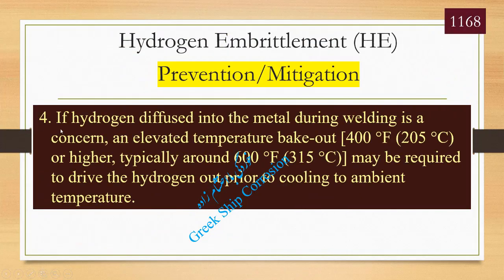3. During welding, use dry, low hydrogen electrodes and preheating methods. 4. If hydrogen diffused into the metal during welding is a concern, an elevated temperature bake out, for example 400 degrees Fahrenheit or higher, typically around 600 degrees Fahrenheit, may be required to drive the hydrogen out prior to cooling to ambient temperature.